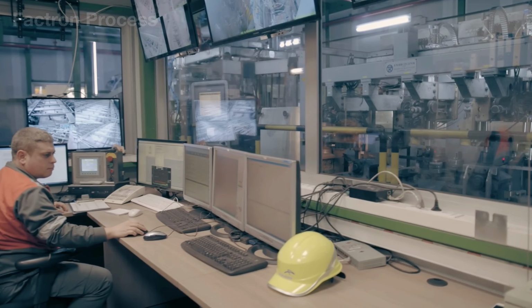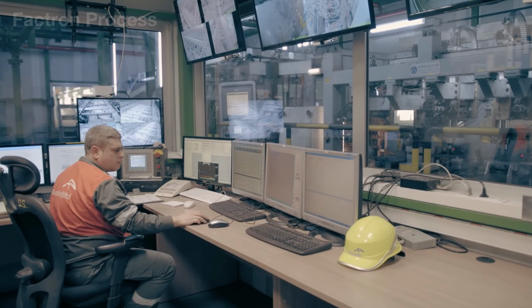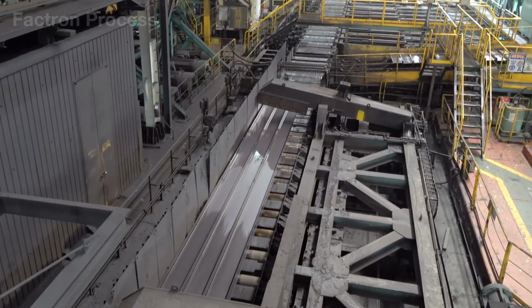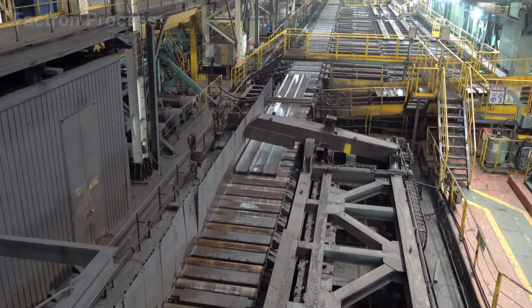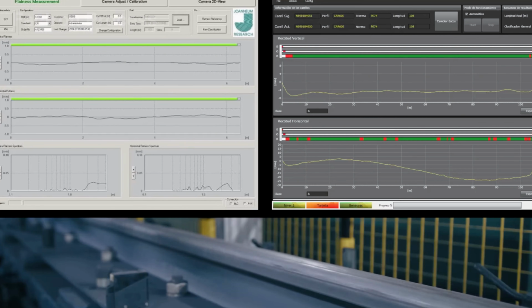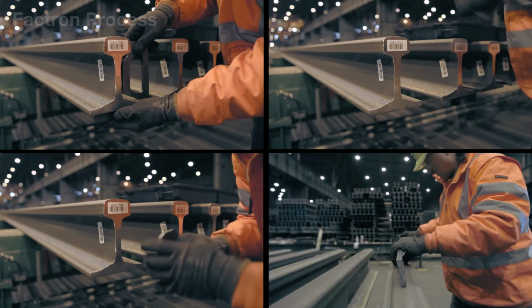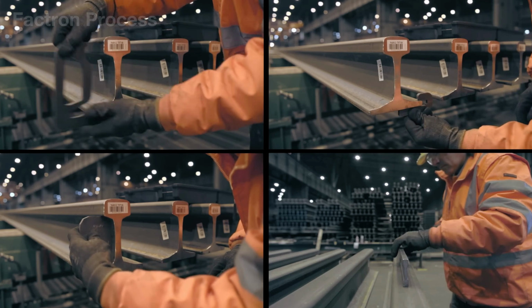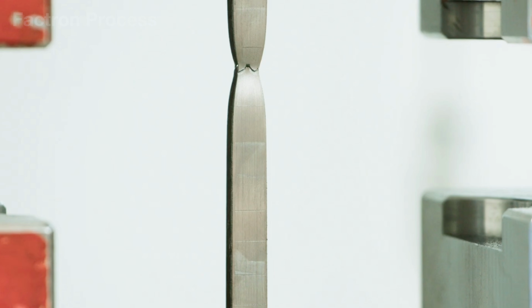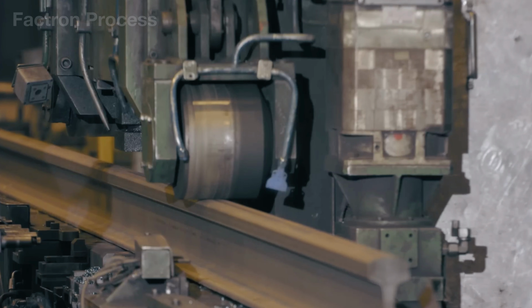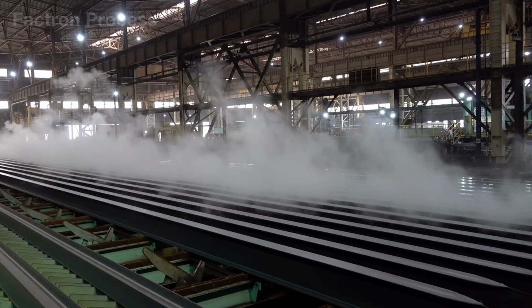At British Steel, 6 cameras can capture more than 4,000 images of each rail, generating over 100,000 inspection images every hour. Ultrasonic probes then scan deep through the railhead, web, and base to detect internal porosity, inclusions, or hidden cracks. Only rails that successfully pass every inspection are marked and cleared for shipment.